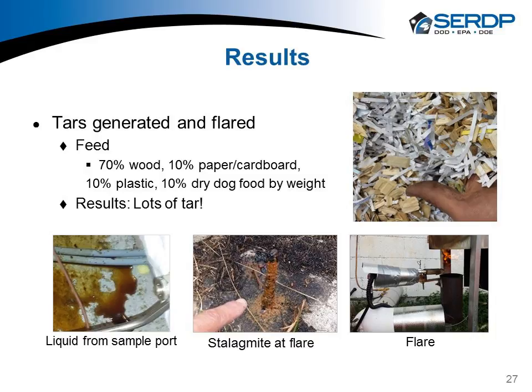So we put a significant amount of wood in there, but then also a reasonable mix of paper and cardboard and plastic, and then dry dog food to simulate military base waste as best as we could without having the odor of true garbage. The results were that we had lots of tar. Depending on the sample port, we could have tar running out all over the place. One of the interesting things was that we grew a stalagmite at the flare. I'll talk about the analysis of that later.